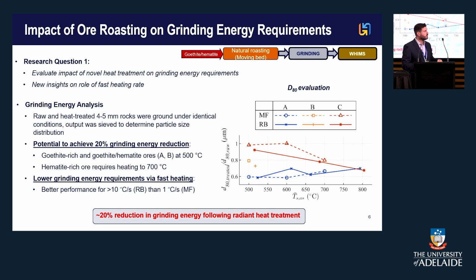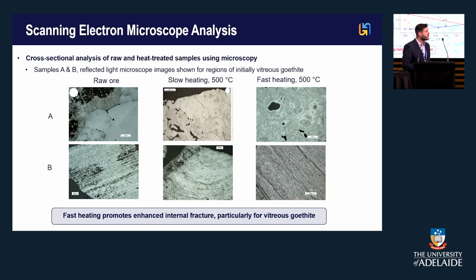As you can also see, the way we provide the heating, fast heating from flux radiation versus slow heating, has an impact on how much grinding energy we can save. And you see why this happens. When you have goethite, the goethite is transformed into hematite and releases all of the OH radicals. This creates a lot of fracturing, but the very fast heating also creates additional thermal stress. So there is strong damage that ends up making the material much softer and easier to grind.